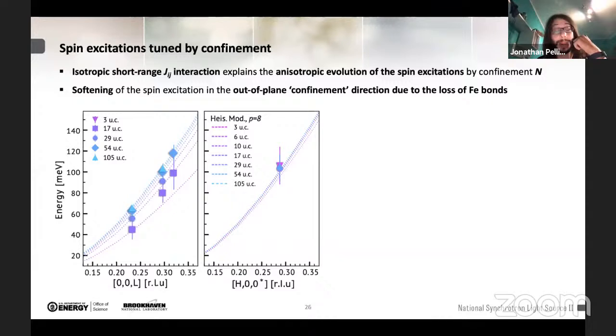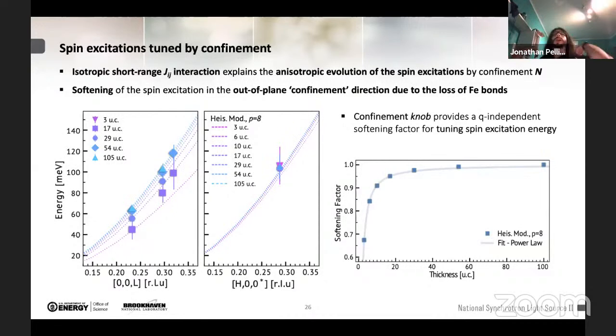On top of this, based on this calculation, we could take a step further, as they are simply based on the gain or loss of iron bonds due to the confinement. So it is a simple geometrical parameter. And what we could do was to calculate a softening factor, which is how much the spin excitation energy changes as a function of thickness.